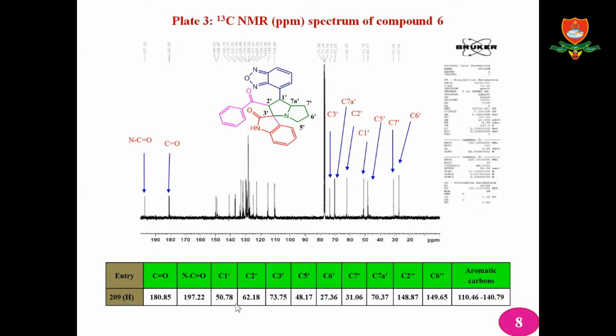Plate 3 shows the C13 NMR spectrum of compound 6. C13 NMR spectrum is used to predict the number of carbons present in the structure. Here, the C=O carbon appeared at 180.85 ppm, NCO carbon appeared at 197.22 ppm. The other aromatic carbons appear around 110.46 to 140.79 ppm.